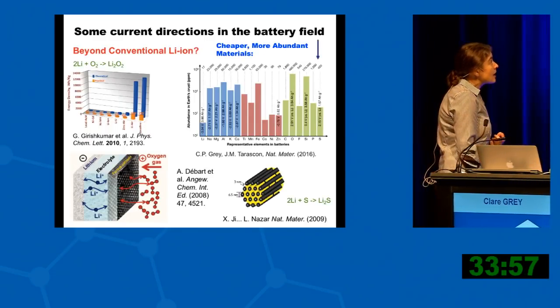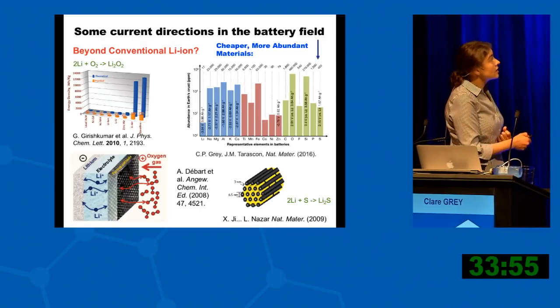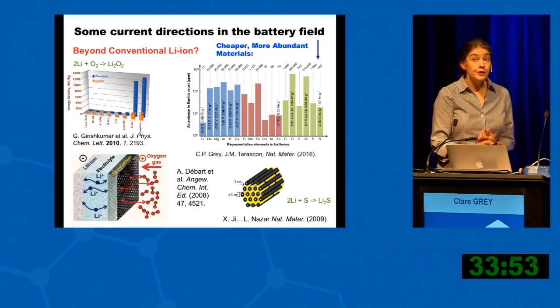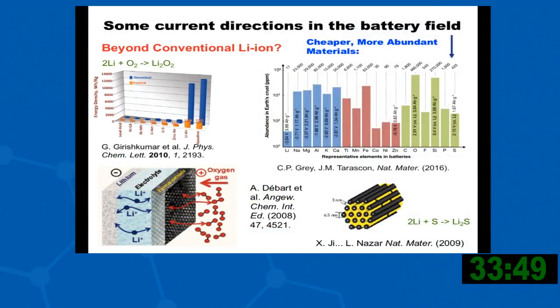Then we can think about moving beyond conventional lithium-ion, trying to use cheaper, more sustainable materials. There are obvious candidates like lithium-sulfur. One of the challenges of lithium-sulfur is that it reacts lithium plus sulfur to form Li2S, and the sulfides formed in between go into the electrolyte, end up on the other side and decompose, so there are issues there.